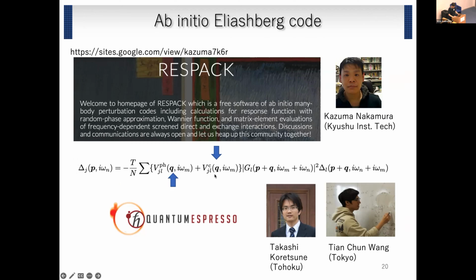And so for the screened Coulomb interactions, we use the code RESPACK. RESPACK is developed by my old friend Kazuma Nakamura in Kyushu Institute of Technology. And this calculates the screened Coulomb interaction with random phase approximation. And this code can also estimate the Hubbard U or Hund coupling using the constrained RPA method. So when we derive a Hubbard U in the Hubbard model, we have to exclude the screening of low energy electrons, and this code can do such a constraint. But in this case, we don't have to introduce such a constraint, and the calculation is a simple RPA.